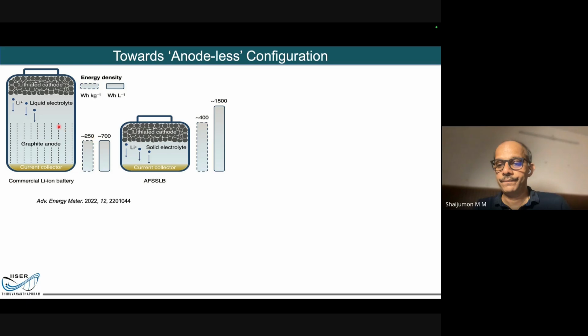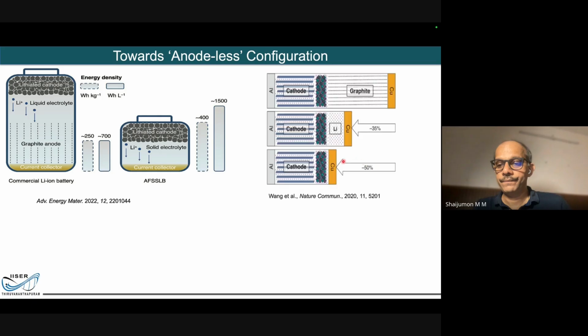Now, as I said, we need to increase the energy density of the battery. If you remember, I was talking about all the ways I can bring down the size and the weight of the battery. And interestingly, it has gone to such an extent. Of course, now we are replacing this with a solid state battery, a solid electrolyte. And now we are saying, look, I don't need this graphite anode at all. Why not just get rid of this anode material, completely take out the graphite anode, and just keep the copper alone.